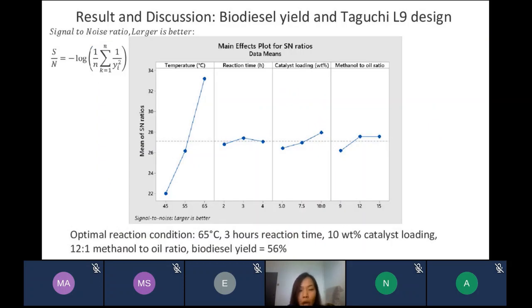Okay, so how can we perform the optimization? The optimization is done by using the Taguchi L9, referring to level 9 design, using the signal to noise ratio, the larger the better. We are plotting the main effect plot of SN ratio, and we can observe that the optimal reaction condition is at 65 degrees Celsius, 3 hours, and 10 weight percentage catalyst loading together with 12 to 1 methanol to oil ratio, which can produce the biodiesel yield of 56%.